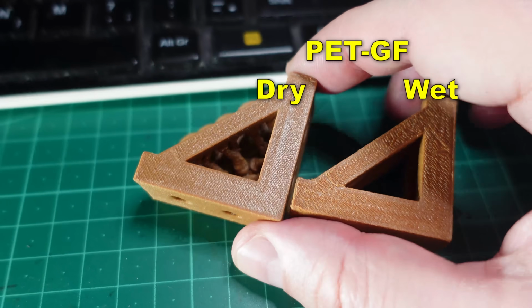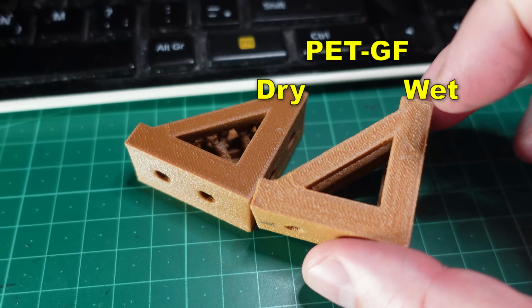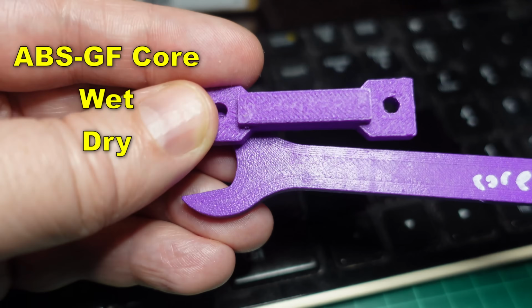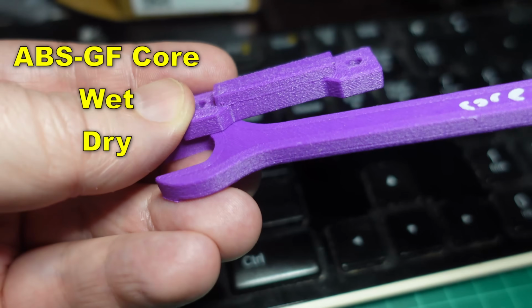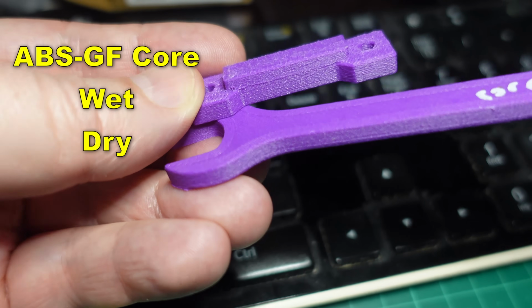Even PLA, ABS is not so sensitive to moisture, but in the fiber reinforced version it is, especially with the core version. I'm not sure why, this is just my experience, but I notice every core filament, if I leave on open air 2 or 3 weeks, I have to dry before the printing, even if it is glass fiber ABS. The reason may be that the moisture will go inside these channels between the fibers and the filament or something like that, but I always notice that I have that over extrusion, very ugly surface, because those micro water drops will boil inside the nozzle and push out more material.